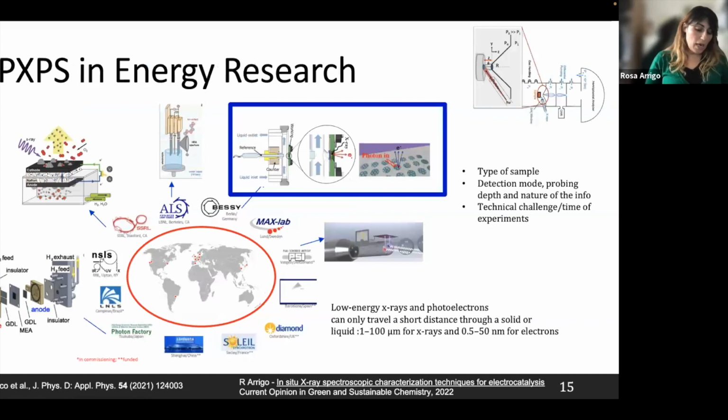Now, the next example is really an application of operando spectroscopy to study this reaction, and particularly ambient pressure XPS. This is basically an in situ XPS, which could be realized by reducing the path of electrons in the high pressure chamber, using a small orifice where the electrons escaping from the surface can go through and enter a differential pumping stage, and be analyzed in the vacuum condition necessary to be analyzed.